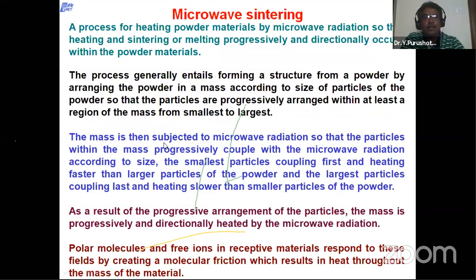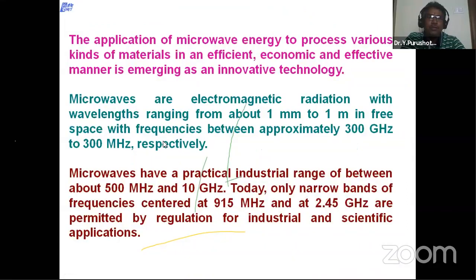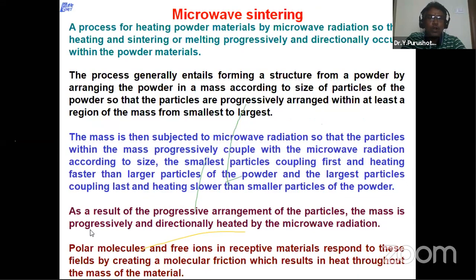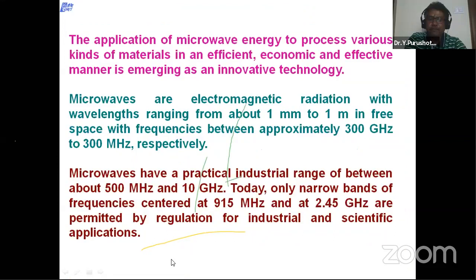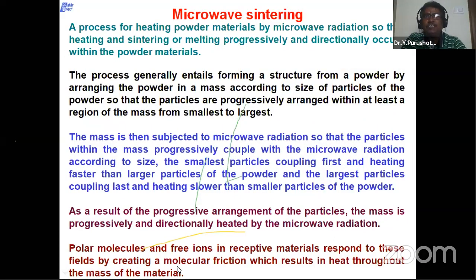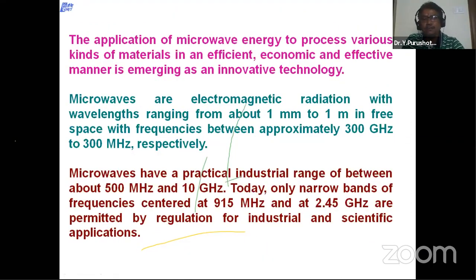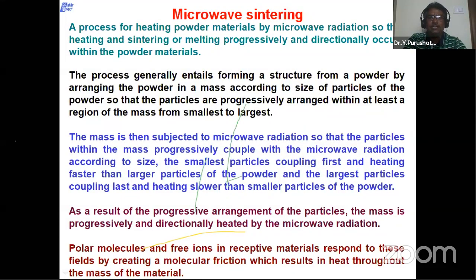Whatever the material to be heated under microwave, the polar molecules and free ions in that material respond to these fields. Microwaves penetrate at the speed of light, such a rapid speed, and these polar molecules and free ions in our material create a molecular friction which results in heat throughout the mass of the material. This is why microwave sintering is very fast: because of molecular friction, the material heats rapidly. Within minutes, we can reach hundreds of degrees centigrade.